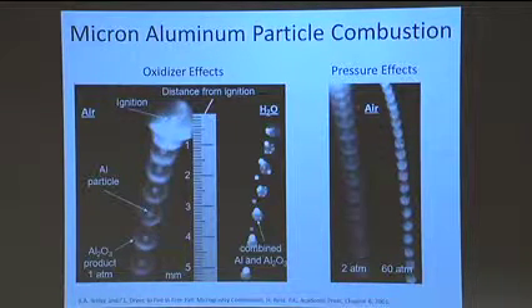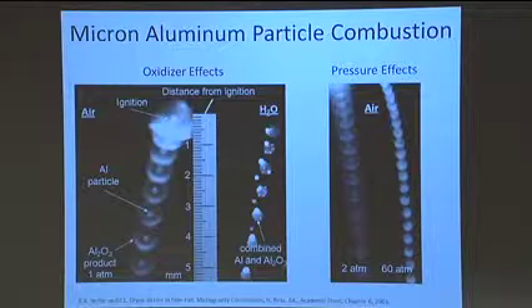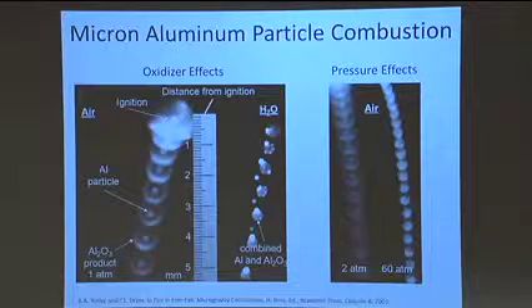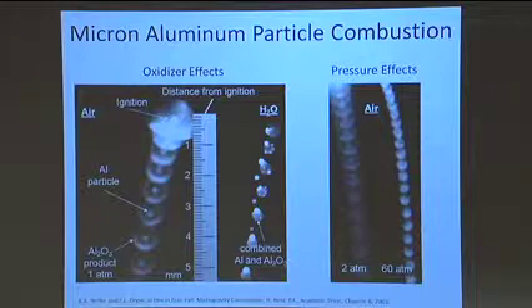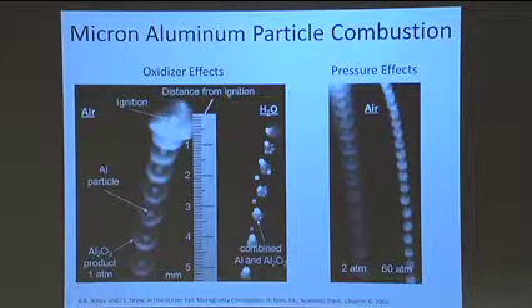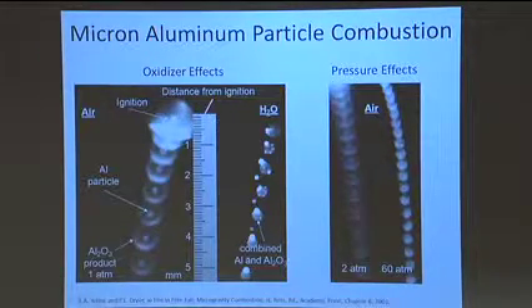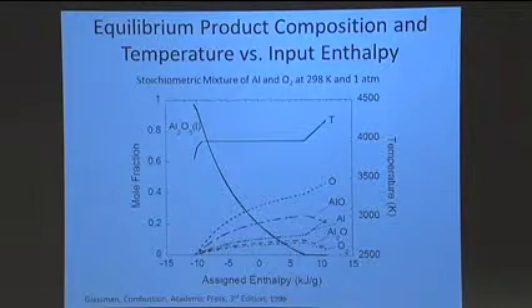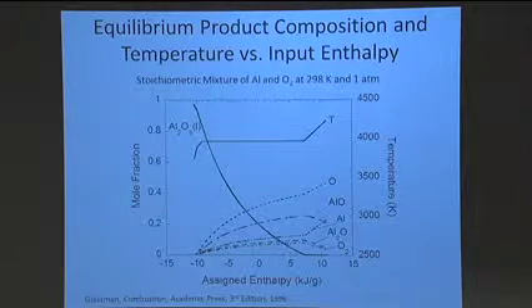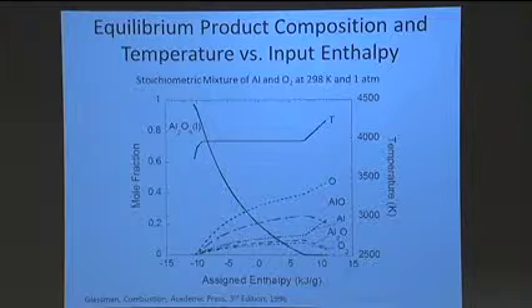And I also show now the pressure effects using molecular oxygen as the oxidizer. Here I'm going from 1 atmosphere to 2 atmospheres to 60 atmospheres, and again you can see it's the same size particle originally, but the flame envelope is getting closer and closer to the surface, and if I were somehow able to do this experiment at higher pressures, the reaction would move right to the surface. So again, showing you how these characteristics change, and this will become important as I look at different oxidizers in different systems later on.